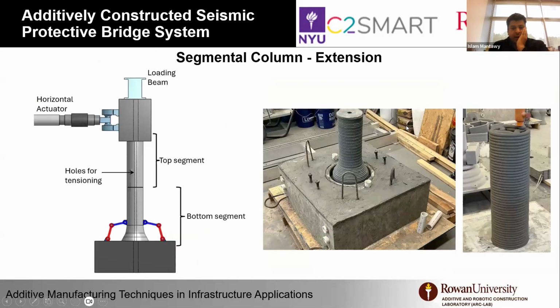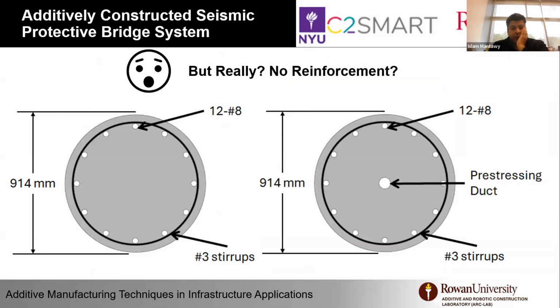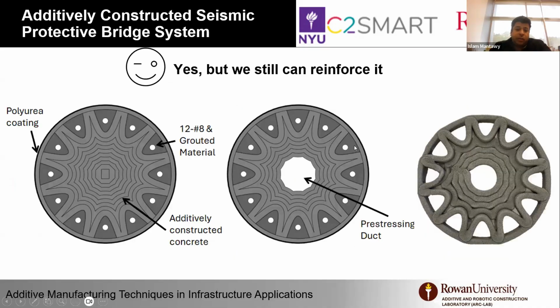So we went back to see how conventional columns in buildings and bridges are designed. Usually you have circular or rectangular columns, with spirals for confinement and shear resistance, and you also have vertical rebars. In a post-tension configuration, you will have an opening in the middle, or duct, to accept the post tension. So what we thought about is to 3D print the majority of the column, leaving a cavity for rebar placement or a cavity for post tensioning.